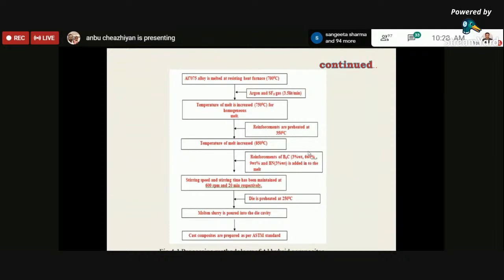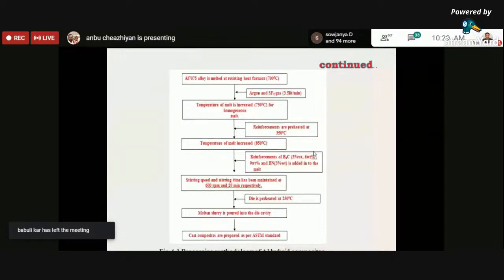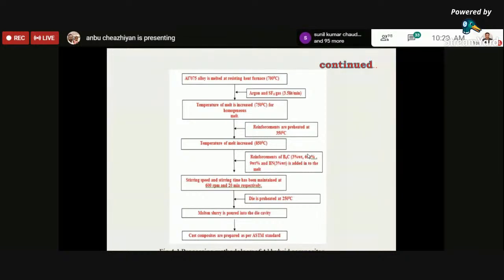Then we added reinforcement of boron carbide at 3%, 6%, 9%, and a constant 3 weight% of boron nitride through an external screw into the molten pool. The stirring speed and stirring time were maintained at 600 rpm and 20 minutes respectively, in order to obtain a homogeneous distribution of reinforcement in the matrix melt. Finally, the die is preheated at 250 degrees centigrade, the molten slurry is poured into the die cavity and allowed to cool at room temperature itself. Finally, the cast samples are prepared as per ASTM standards.